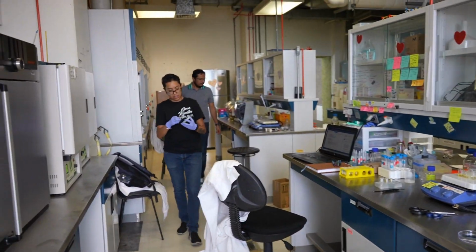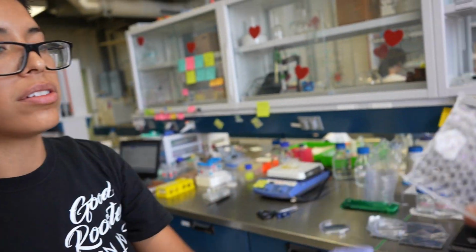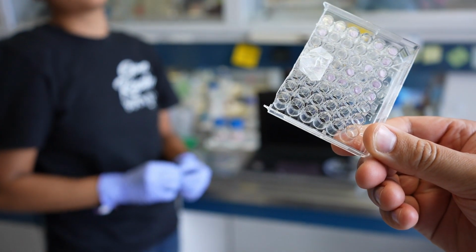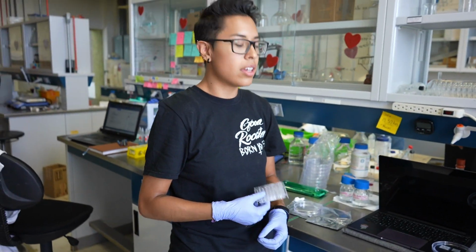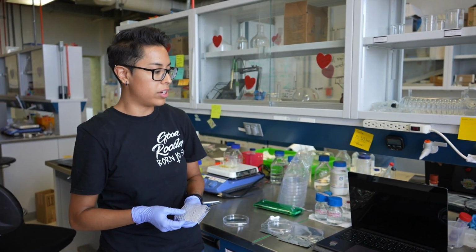Here, like this kind of sponge-like substrates in order to collapse them with the analyte. The thing is that they have hydrogen bonds between them, and when you add the analyte in water, they collapse, and so they have a higher concentration of hotspots between the nanoparticles. And they have a very good SERS response. That's what we're evaluating here.